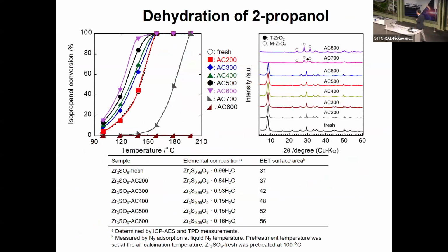Then we started using it as a catalyst for testing the solid acidity. Isopropanol dehydration is a very simple reaction, but very easy to conduct. This shows the catalyst has very high activity, as you can see on the left-hand side. The fresh sample means no calcination, and it shows activity on this line.